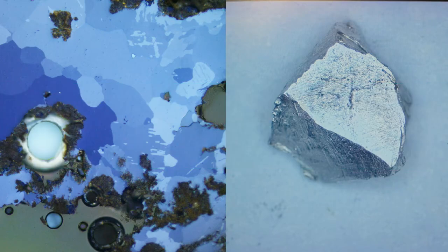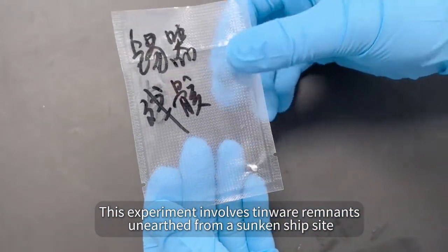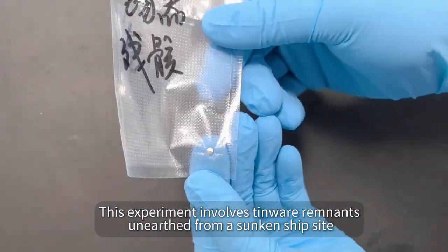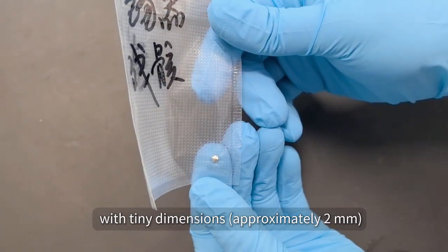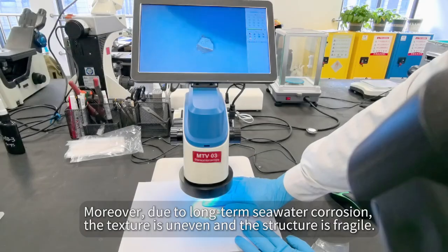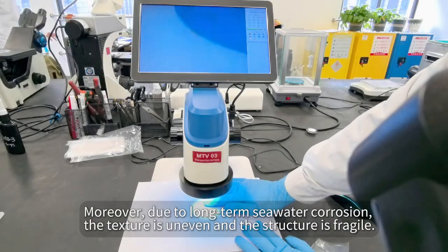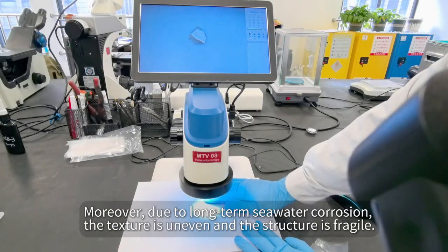Remains of tinware. Metallographic sample preparation and microstructure observation. This experiment involves tinware remnants unearthed from a sunken ship site with tiny dimensions of approximately 2 mm. Moreover, due to long-term seawater corrosion, the texture is uneven and the structure is fragile.